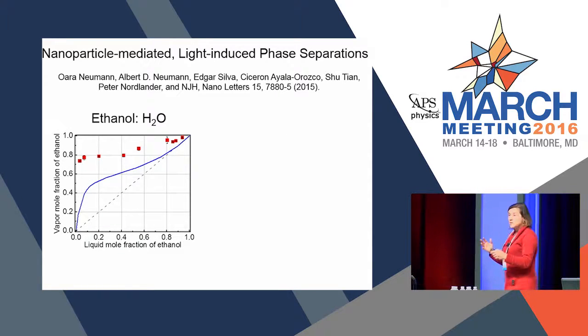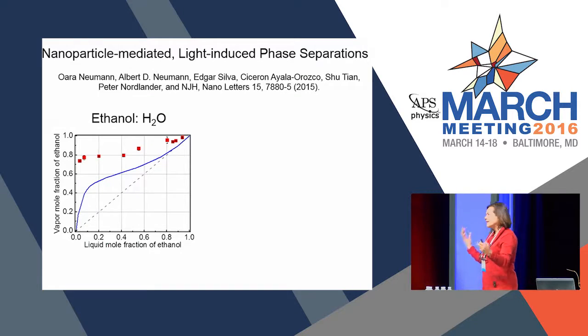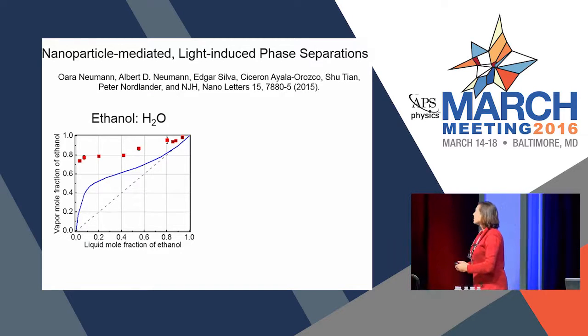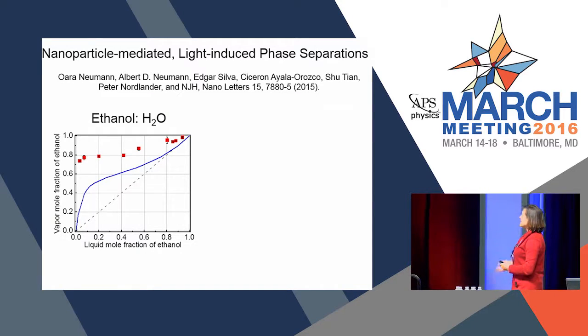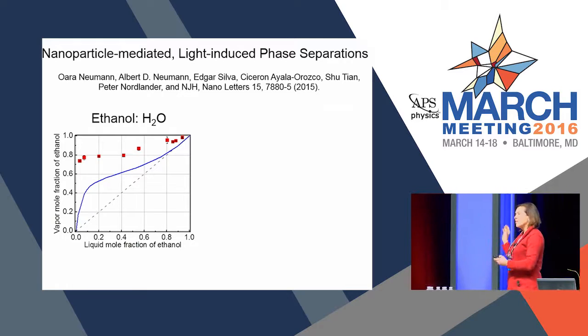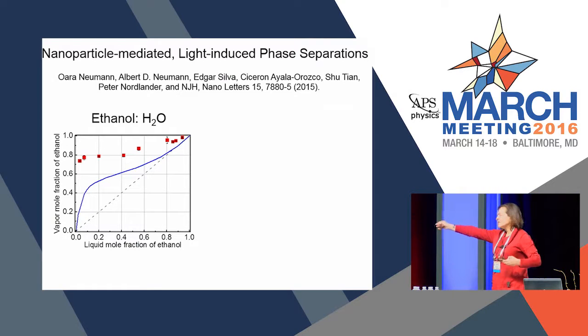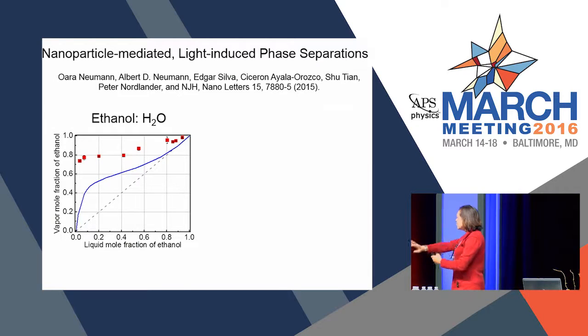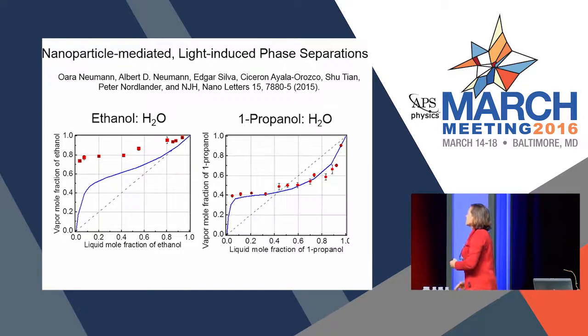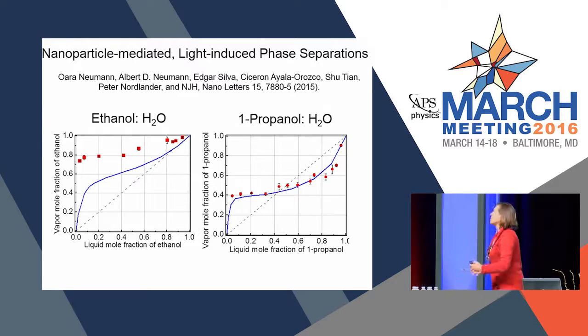So we thought this was wonderful. This is a revolution. We'll completely change the way in which liquids get distilled. So we have this remarkable result with ethanol. We added 1 carbon to the chain of the alcohol, and instead of having ethanol, we had propanol, and a propanol water mixture, it turns out, was identical to the thermal result.